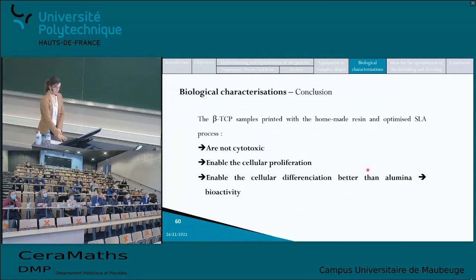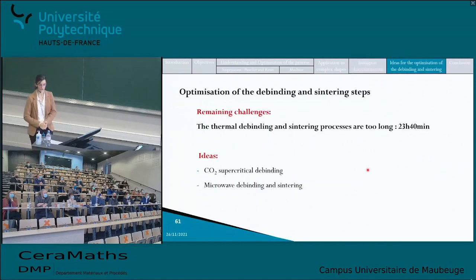So the final, however, even if the process was optimized, there are still some remaining challenges, because the thermal debinding and sintering processes were very long, 23 hours and 40 minutes. So the idea was to try and use two different new technologies, the CO2 supercritical debinding and the microwave debinding and sintering, and to see if these technologies could be used with the SLA process.